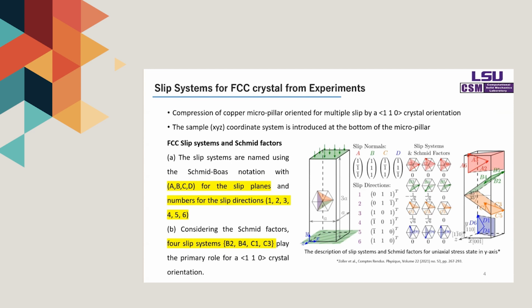Slip systems for FCC crystal and experiments: copper single crystalline specimens are prepared for micropillar compression. The figure shows the description of typical FCC slip systems and Schmid factors for a uniaxial stress state along the y-axis.